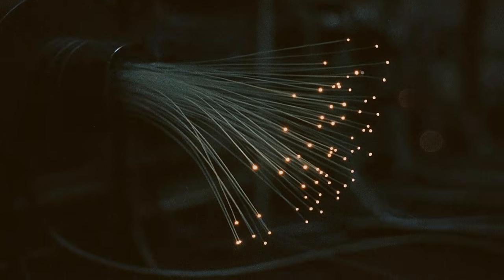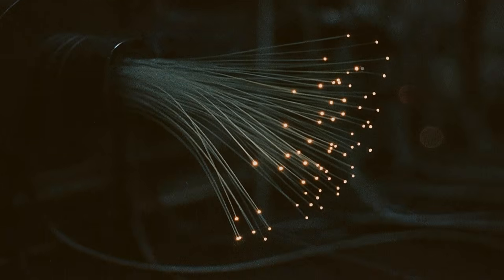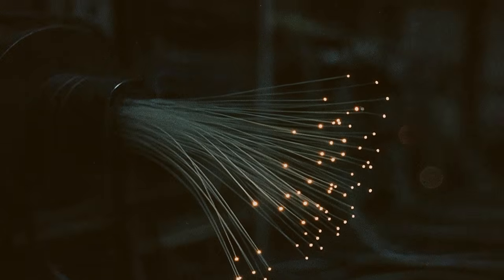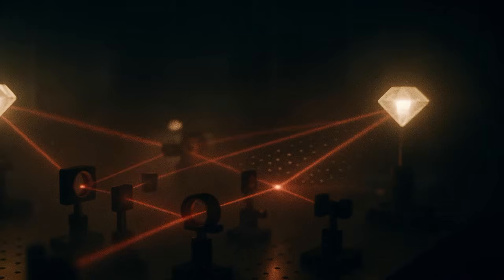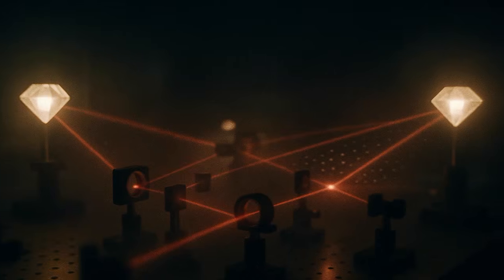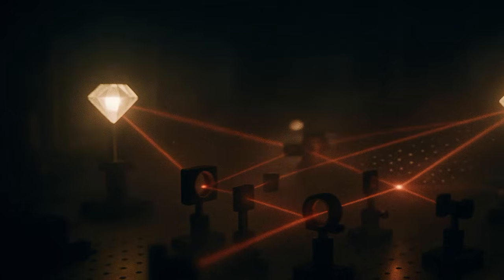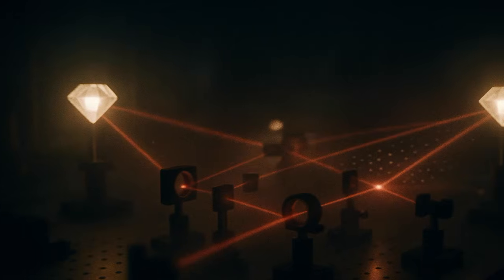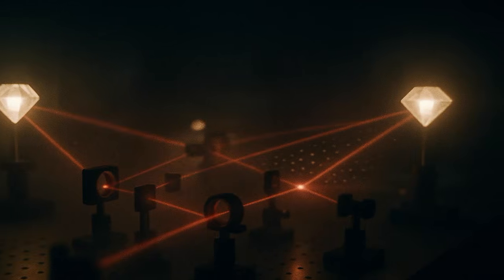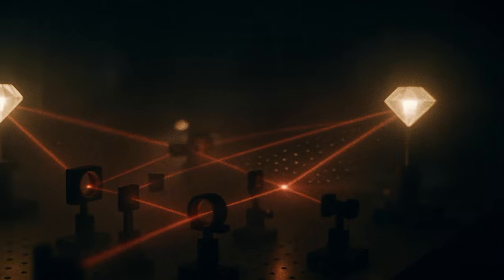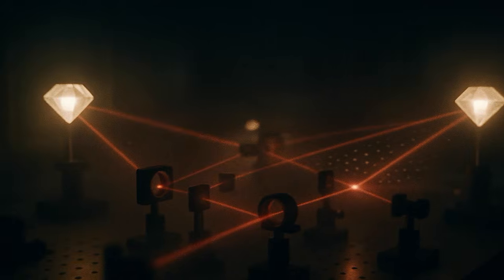Thermal expansion coefficient of diamond is 1 times 10 to the negative 6 per Kelvin, compared to silicon at 2.6 times 10 to the negative 6, or germanium at 6 times 10 to the negative 6. Diamond lattice is locked in place. That rigidity preserves the electronic transition energy against thermal noise. The zero phonon line shifts with temperature, but it doesn't wash out.